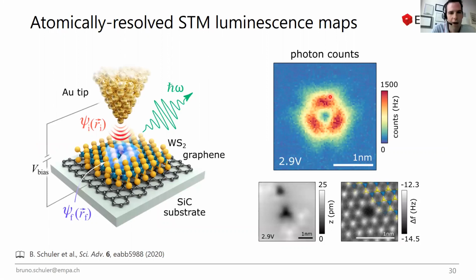Okay, excellent. The last part is where we try to induce electromagnetic excitation and look at the optical response. That's a simple cartoon. Again, we parked our tip on top of a defect, in this case the sulfur vacancies that we created, and injected at higher electron energy, so higher voltage, and looked at the photons emitted in the far field. By doing this, we could record what we call a photon map of a single defect. This has nothing to do with the topography or the AFM, of course, but is really an optical excitation of this junction.